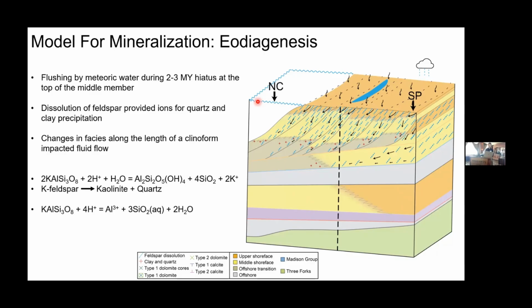So this is the first time step. This is shortly after or during deposition of the middle member. As I mentioned previously, there was a 2 to 3 million year hiatus at the top of the middle member, which resulted in meteoric influx into the Sappington, which resulted in the dissolution of feldspar and provided some ions for quartz and kaolinite precipitation. That's represented on the figure here by these dashed blue lines, which represent areas that had feldspar dissolution. And then the cements will be in these crosses in red.